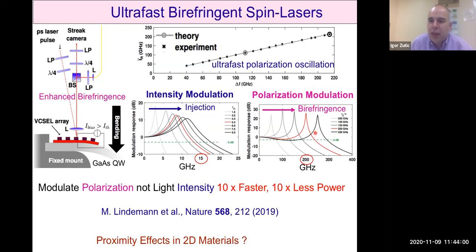So it's as if someone is quickly talking to us in a foreign language. We just ignore that person. But for spin lasers, this birefringence allows them to reach a resonance that can be controlled as the birefringence is increased. And here, these are basically experimental values by introducing strain or deformation of the sample. We can then make this birefringence extremely high, several hundreds of gigahertz, and while we stopped at 200 gigahertz, because this is now close to destruction of the sample, we don't know what the limit is. So maybe we can go to the terahertz regime with a different material and different approaches. Already 100 gigahertz is something that is just not possible for room temperature semiconductor lasers.